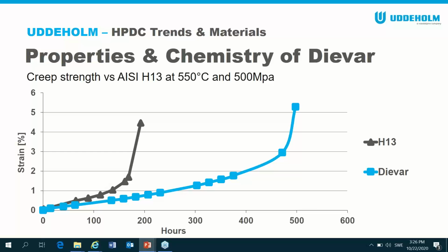And finally, we come on to creep strength. So creep strength, again, this is a force, 500 megapascal, with temperature, 550 degrees C, and over time. And you can see, if we equate this to a core pin, so you can picture what's happening here a little bit more in your head. If you take a core pin at constant temperature, it's being heated up. Over time, that pin can start to move, okay? And what this is showing you is Dievar takes much, much longer to start to deform. This is one of the reasons why it's used in extrusion, for example, for heat sink dies, because Dievar doesn't flex so much over time and temperature.